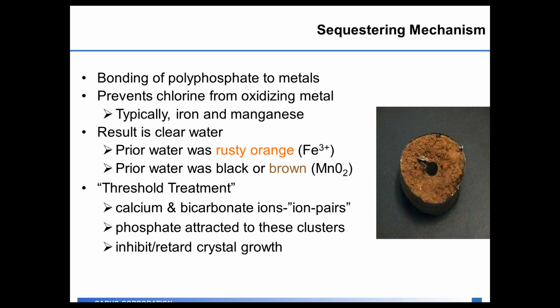The other application would be threshold treatment for calcium carbonate scale control. The idea here is you keep the calcium and bicarbonate ion pairs from clustering to where they'd actually form a crystal and plate out and cause that distinctive white scaling you would see on the distribution system. The idea here is just enough phosphate to inhibit the crystal growth so you don't get the scaling issues you would see with calcium carbonate.